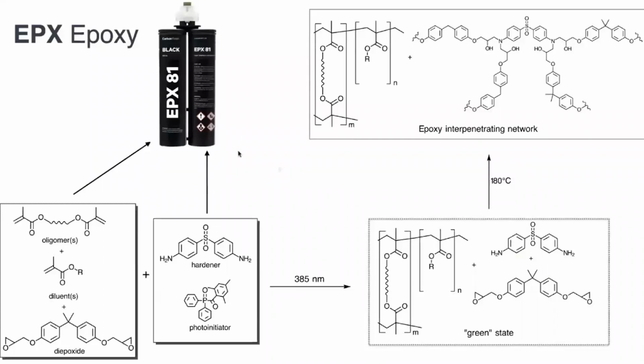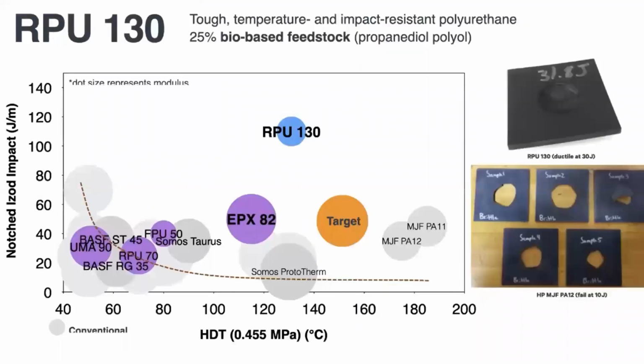This is a generic approach for doing that, where we basically take advantage of orthogonal chemistry, a free radically polymerized system shown here with a dimethacrylate approach, having a system of photoinitiator to polymerize that, but also combining this with diepoxides and diamines so that when light hits it, we can set the shape with light, but then we have this latent chemistry and basically do a solid state polymerization in the form of the part to generate our particular part with very good properties. And with that, you can make amazing materials with a wide range of properties, including rigid materials with great ductility and high strength and high glass transition temperature, heat deflection temperatures.